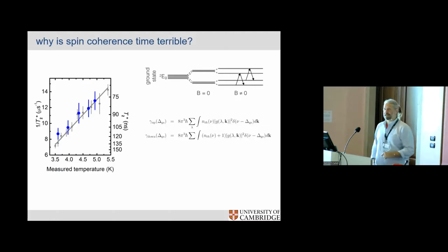So what's happening in the system, interestingly, is think of it as from now on, any group 4 color center you hear about that's in this category, I'll do a spoiler, think of it as a single electron in a double potential well, okay? So that means you will have these orbital states split by the tunnel rate between them, effectively. And then what it gives you is, unfortunately, this phonon-assisted either spin flip or not even spin flip, but phase flipping or phase scrambling phononic transitions.